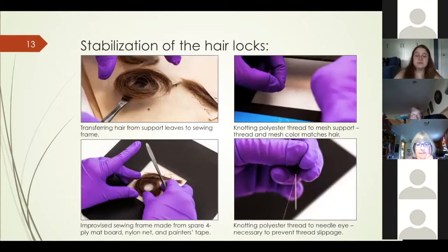The netting needed to be held at even tension so the hair wouldn't pucker after stitching. An embroidery hoop would have stretched the hair too much, causing uneven tension when released. Instead, I used a window mat cut from black mat board — a small square of net was attached to the mat board using painter's tape, which held the textile flat with minimal tension and could be removed easily so both mat and tape could be reused. Once the netting was attached, I flipped the board over so the hair could nestle inside the recess of the window mat.